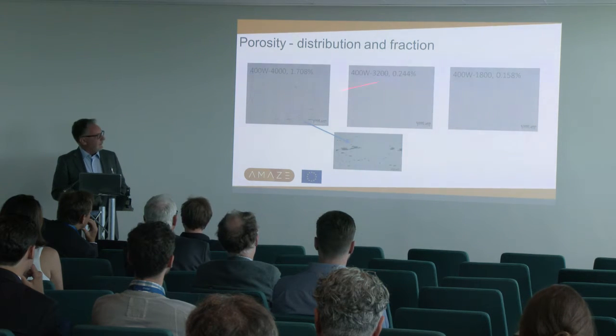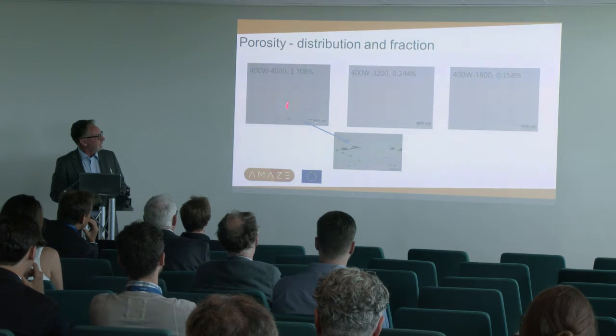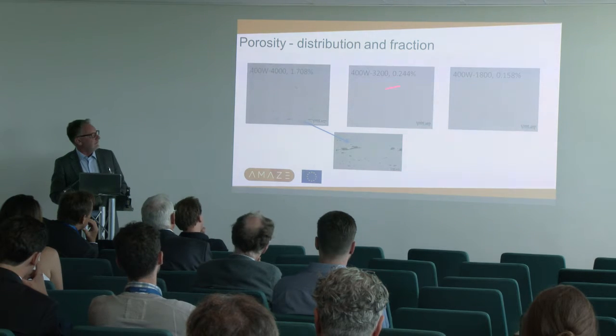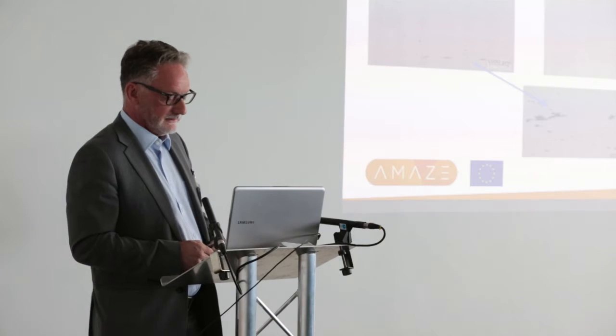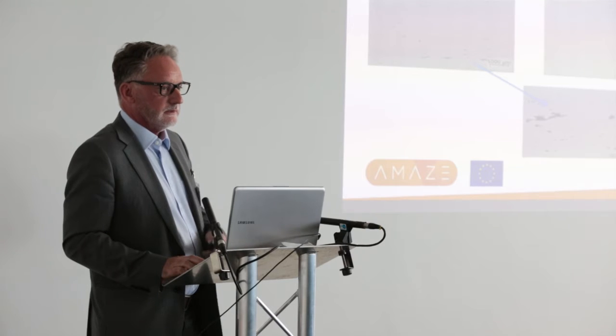So you can see that if you're scanning at too high a speed, then you get lack of fusion defects. But as you slow down and increase the energy density, then you can get to very high density parts. And the material has a very wide processing window.